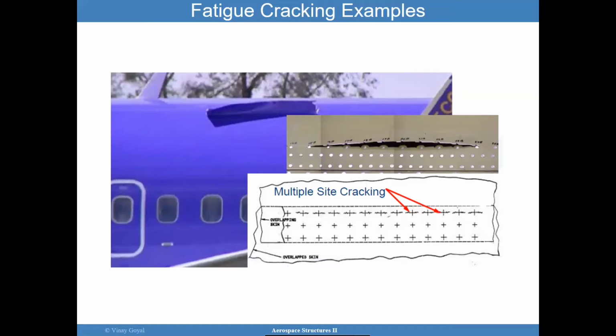And so you may not be able to use hours in service as a good metric for inspections because of that. As a consequence, this particular situation had to be revisited, because clearly fatigue from a hole was a particular concern, and it was driven really by the ground to takeoff and ground to air cycles, back to ground. That's one cycle. That's one complete cycle.